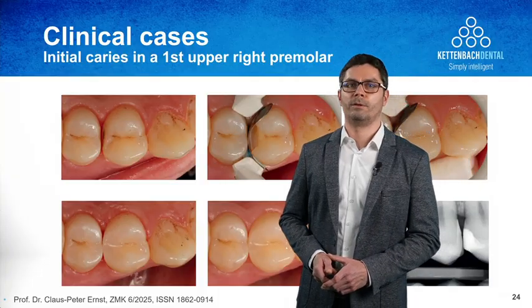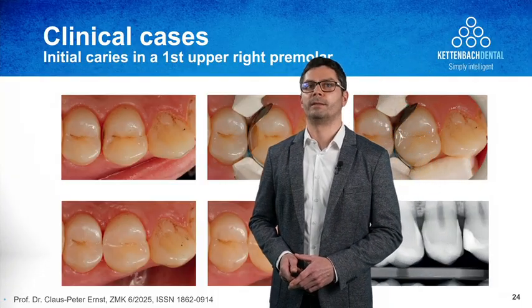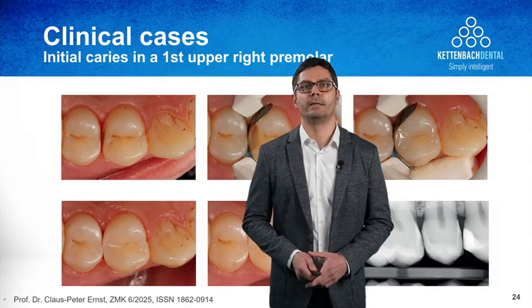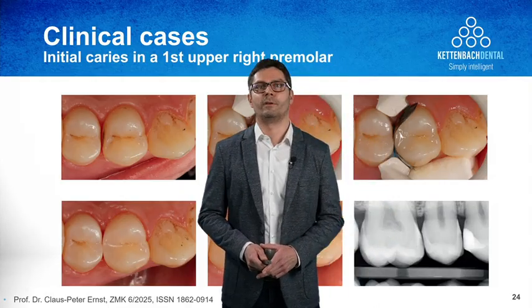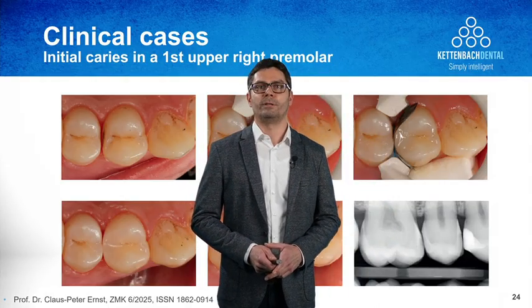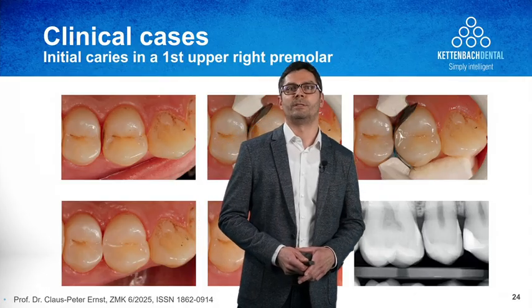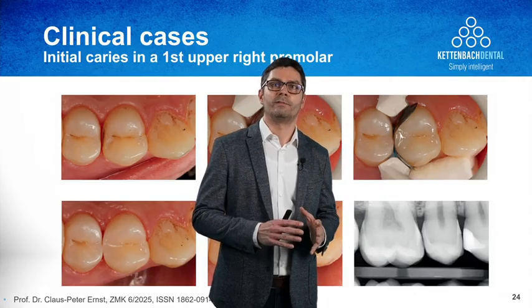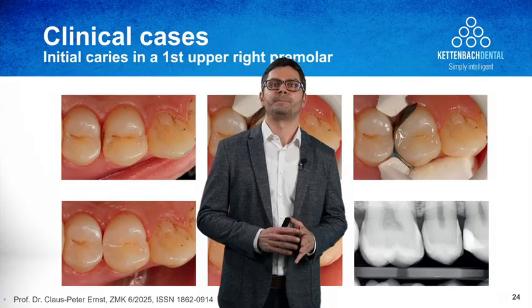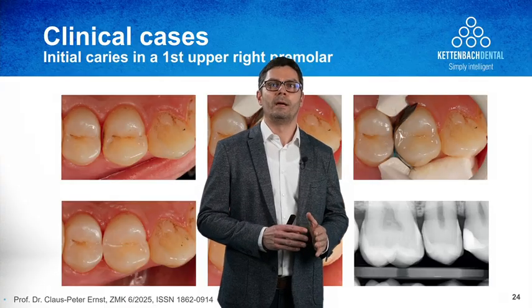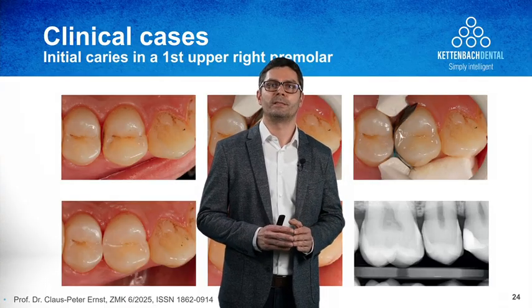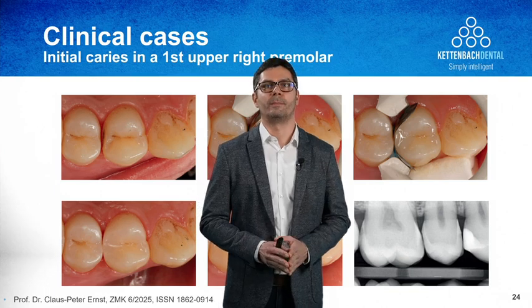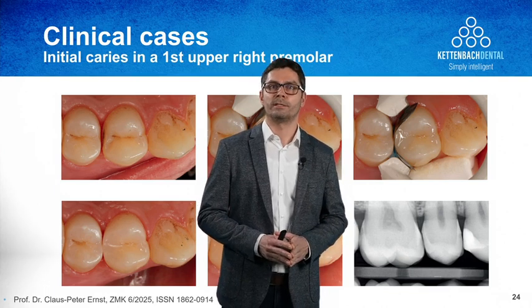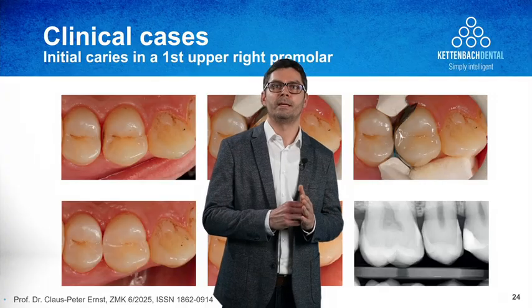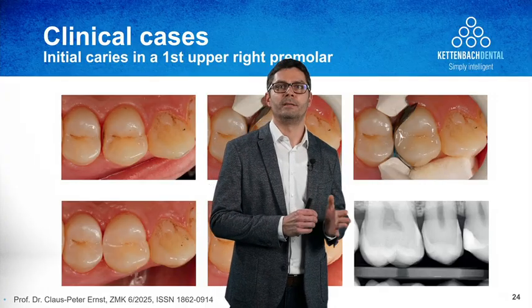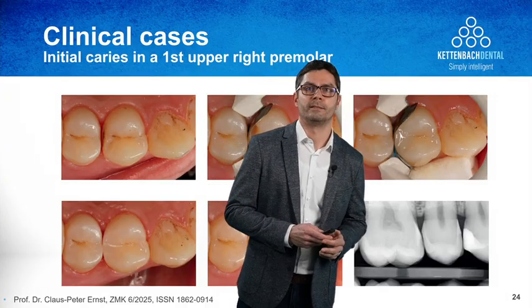Another case that I wanted to show you is this one here. Once again, a cavity with caries inside it, which was nicely prepared and then filled with our material. What I wanted to show you here is the nice adaptation of the material. Our material, Visalys Bulk Flow, is a flowable bulk composite. So it is flowable, but at the same time has a nice consistency so that it doesn't slump around if you are on the upper tooth, for example. It has a nice flowability to adapt nicely to the cavity walls, as you can see here in this radio image on the right hand side.